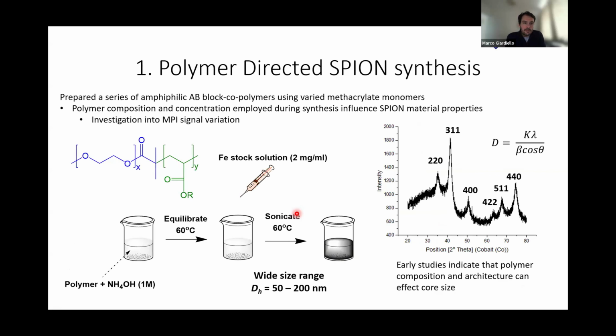So just to go into the first method, we're doing it via both methods. This is the co-precipitation, but we also use thermal decomposition. So this is polymer-directed SPION synthesis. We are now investigating the effect of amphiphilic AB block copolymers, so polyethylene glycol with methacrylate polymers made by a method called ATRP, which is atom transfer radical polymerization. It's a very controlled method of making linear and also branched polymers.